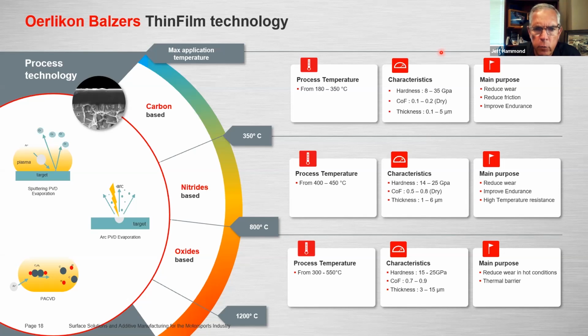Okay, we got another question here from John Damasowicz, and he's wondering, are there any machinability issues with any coatings? Again, 3 micrometer here in this case. Sometimes we coat parts which are not fully machined, fully finished, but for some reason it's easier to coat the parts at a certain stage. So we apply the coating all over, and then some very specific areas are machined afterwards. And therefore, again, it's only 3 micrometer. As soon as you get inside the material under the coating, machining will be almost as usual, and the coating won't break. It's not because you're going to machine that you're going to have the machining line, the coating will start to come off or whatever. Right. It will be a clean machine, clean line.